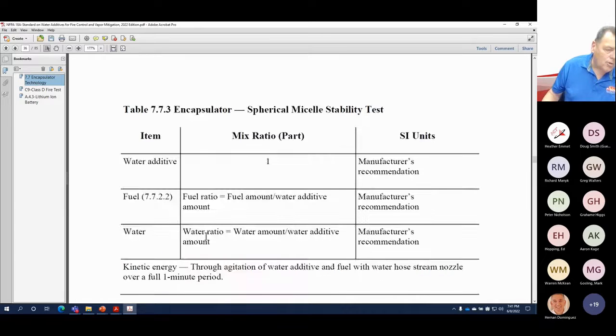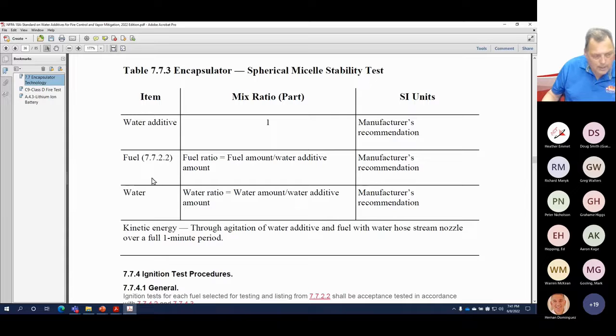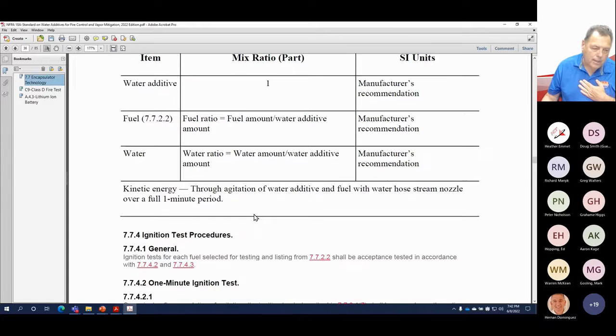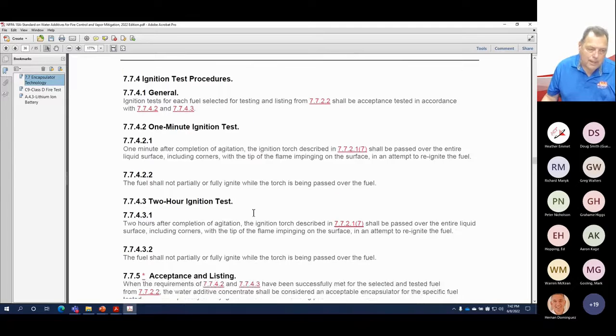So what this is doing is we're putting in the water additive, the fuel in the water, we're mixing with kinetic energy. Our ratio that we use is 1 part of F500, 8 parts fuel, 40 parts water. So 1/40 is 2.5%. And the appendix talks about that. But there's a 1-minute ignition test after the agitation, but then you have to come back 2 hours later and put the torch to it. And it can't ignite after 2 hours.